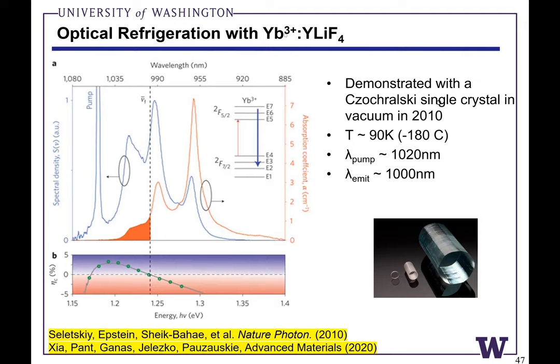This is your ytterbium-3+ ions in a ceramic yttrium lithium fluoride, a laser gain medium. Some of you may have a YLF laser in the lab right now, but effectively just shining a continuous wave laser on this laser gain ceramic, you can pump electrons in the ytterbium-3+ ions. Effectively, you absorb one photon from the pump laser. You create a long-lived excited state that can radiate a new photon that's blue-shifted relative to the pump photon that was absorbed.